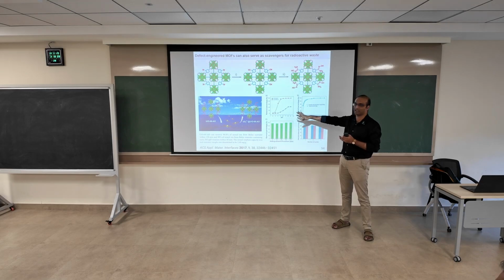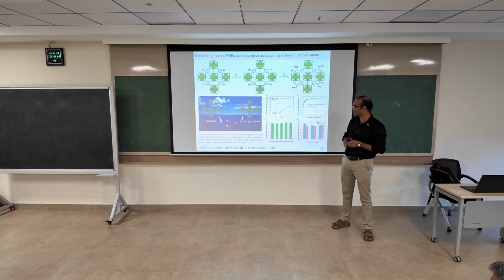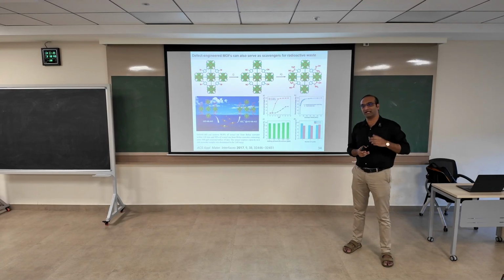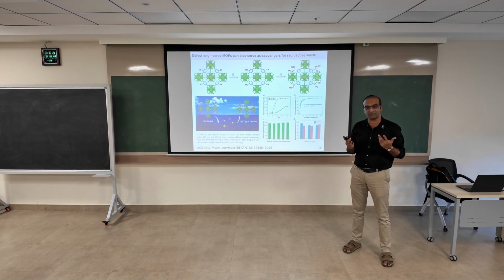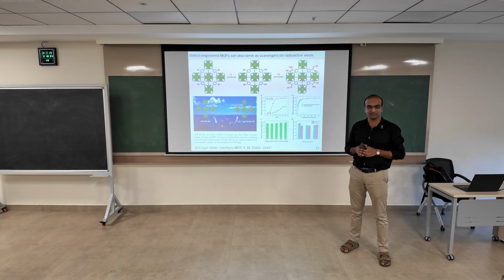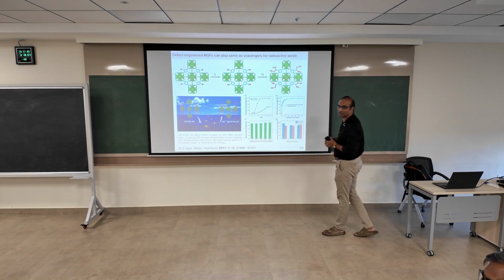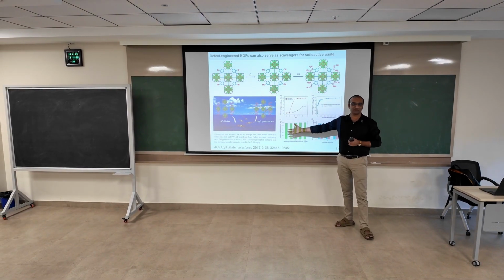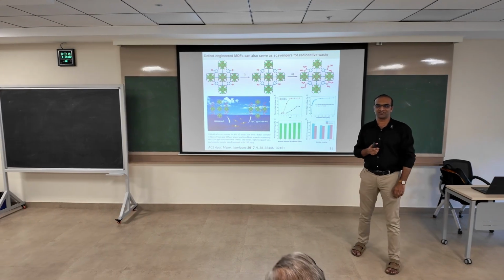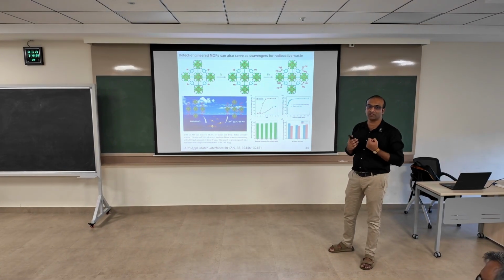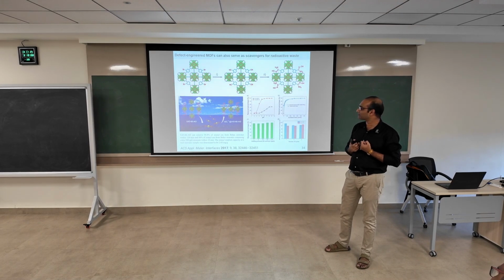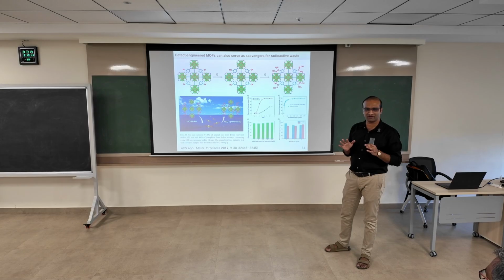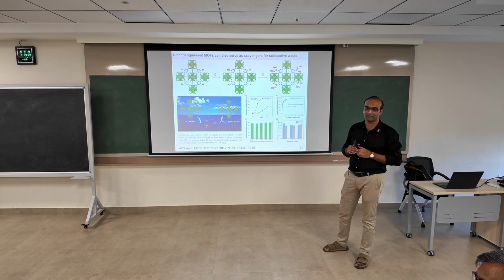This is one application. I don't think it will ever reach commercialization in our lives, but it's one way of looking at it. The concentration of uranium is not that much, parts per billion in the field. But if you collect it and keep on collecting, you can get as much as possible. It's parts per billion, but you can use these MOFs to selectively take it. They adsorb the uranyl very fast, and then you can convert it. I think in the next 100 years we have uranium supplies in many parts. I don't think we have infinite deposits, but we have a lot.